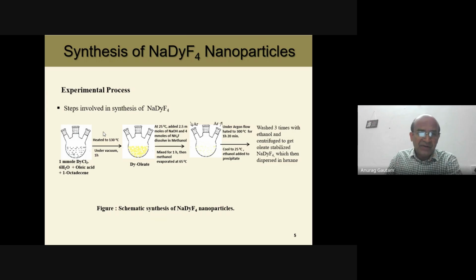Basically, this material was synthesized with 1 millimole of dysprosium chloride. Dysprosium is a rare earth. You add water, and then the required amount of oleic acid and octadecene. Oleic acid and octadecene are surfactants. You add all the material under vacuum and heat it to 130 degrees centigrade. So they will convert to oleates. Dysprosium oleate will form, and then you cool it down and remove the vacuum. All should be removed. Cool it down.